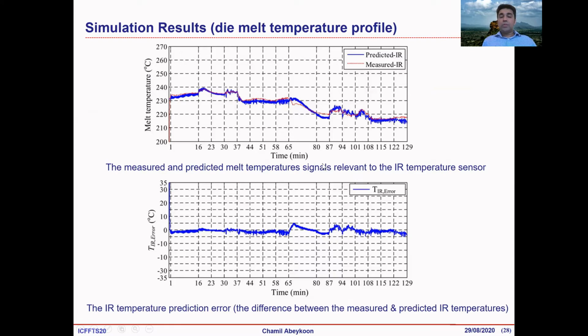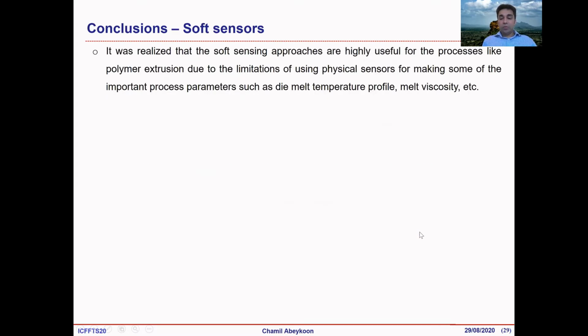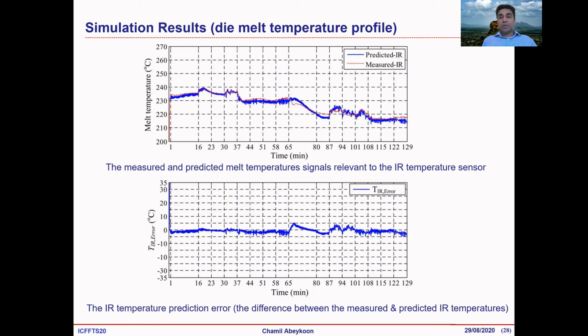So this is about the error signal, predicted infrared and measured infrared. It's quite pretty good. You can see the time here. We have been testing this sensor for more than 2 hours. It's working quite fine. This is the error here. The TIR error is quite small. Okay, so based on that, this is the first soft sensing approach proposed for die melt temperature profile prediction in polymer extrusion. It is showing very good results at simulation and testing stages.